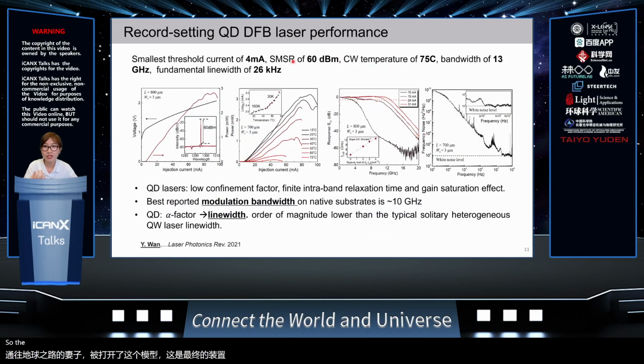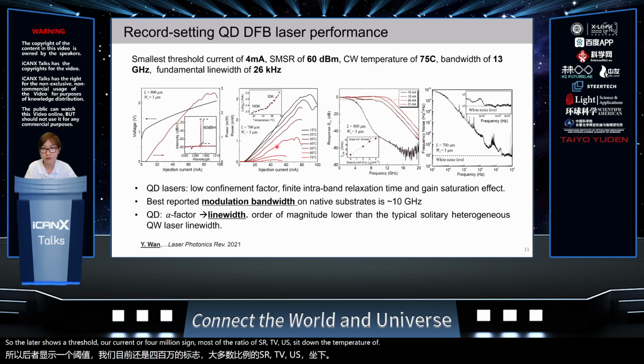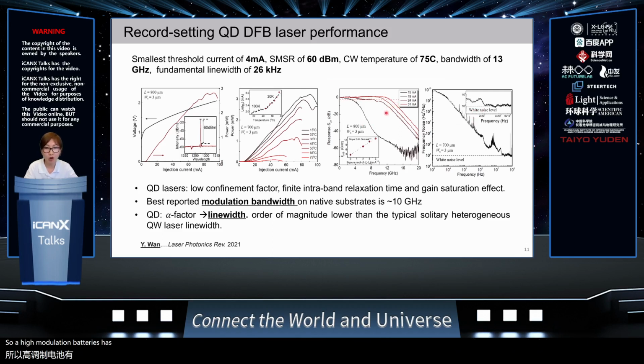The laser shows a threshold current of 4 milliamps, a side mode suppression ratio of 60 dB, and a CW temperature of 75 degrees C. But what I want to emphasize here is the modulation bandwidth and the linewidth. A high modulation bandwidth has always been very difficult to attain for quantum dot lasers.